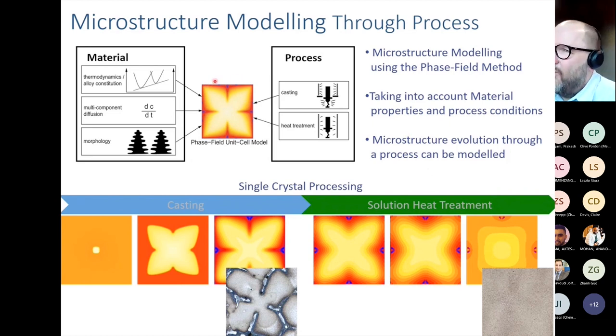I'm not yet going into the details of how the coupling is done, but the idea is that we have the morphology from phase field. We have the diffusion equation, which in the simplest case would be Fick's equation or a thermodynamic formulation thereof. And now we substitute the phase diagram with thermodynamic calculations using something like the CALPHAD approach. CALPHAD is actually a very good approach for that.